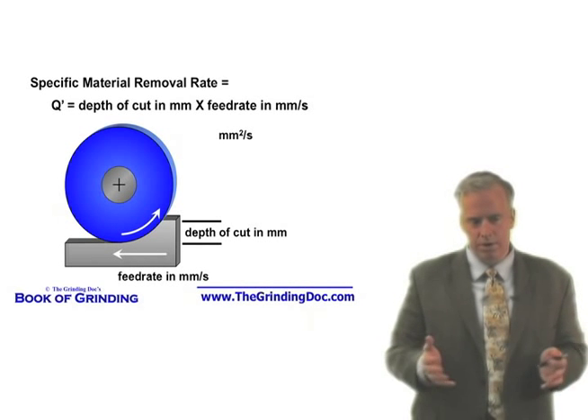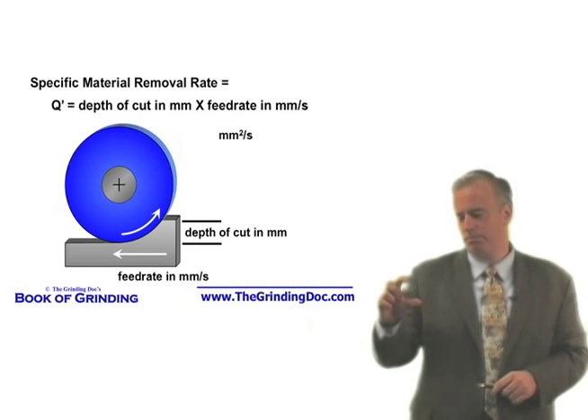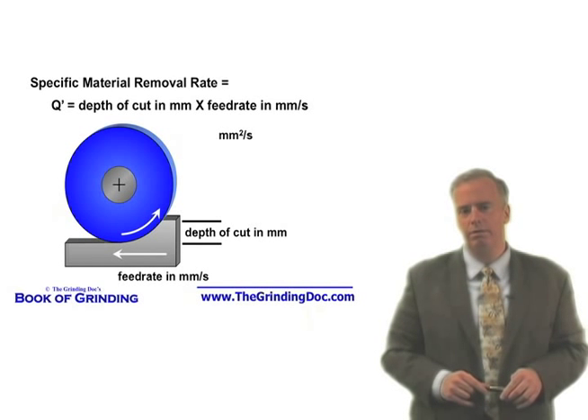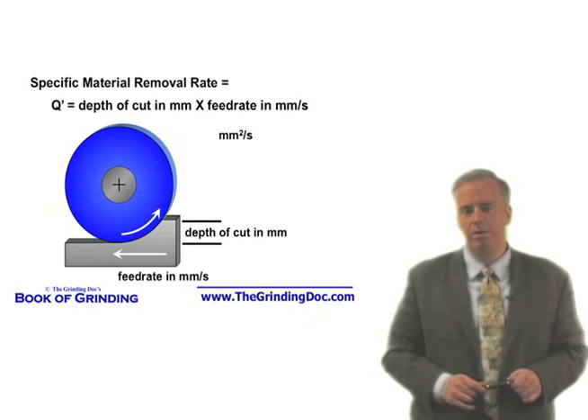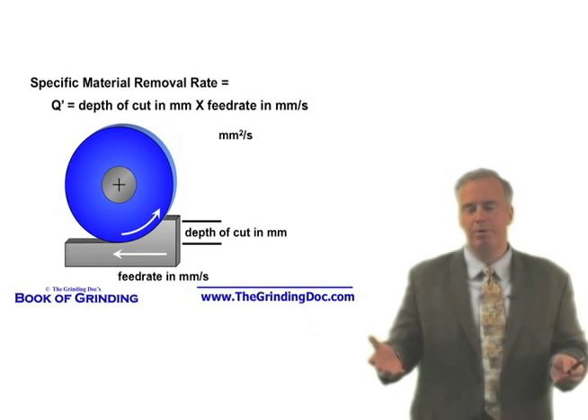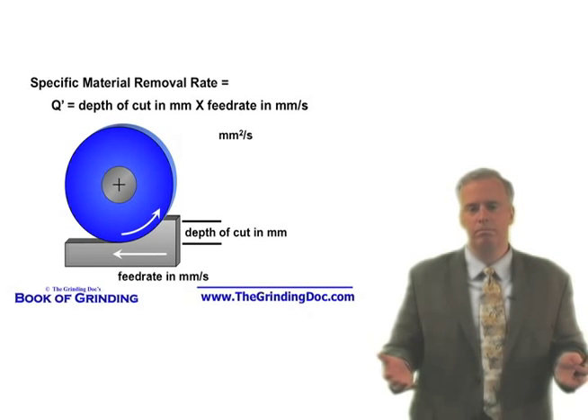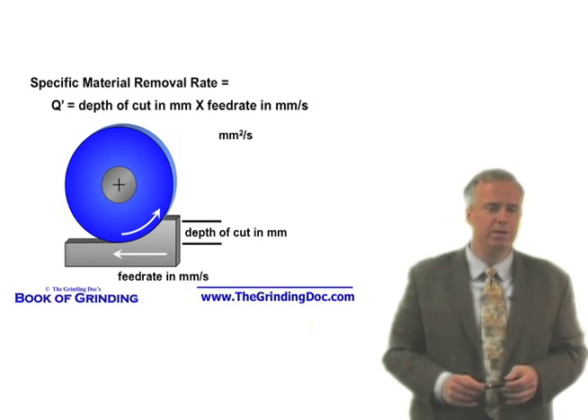You can go to your grinding operations — you're grinding different diameters of tungsten carbide end mills, sometimes one inch, sometimes an eighth of an inch — do the calculations and say, what's a good value for this wheel? What can this wheel tolerate? Wheel suppliers will say: this new resin bonded or hybrid bond wheel can get Q' values of around seven. That's about the ballpark you should be looking at for that particular wheel.